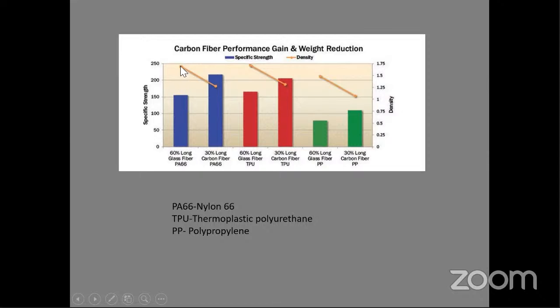When it comes to the densities, here the density of the glass fibers are higher, the carbon fibers are lower. But from a cost point of view, carbon fibers cost is high. Again, if you see when you are changing the polymers, the strengths also vary due to the polymers. Like you can see it, the first material having almost 150. When you change the polymer, the strength is increased. And when you change one more polymer, the same compositions, the strength is decreased. So the densities are slightly varying, but if you see the values, due to change in the polymers also, the properties are varying. And due to the percentages changing also, properties are varying.